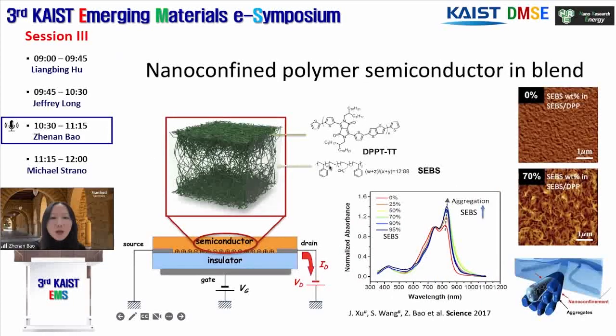And upon further investigation, we discovered that, in fact, with proper choice of the insulating polymer, here, we want to have them match the surface energy of the semiconducting polymer so that there is no dramatic phase separation that will lead to isolated semiconducting regions.